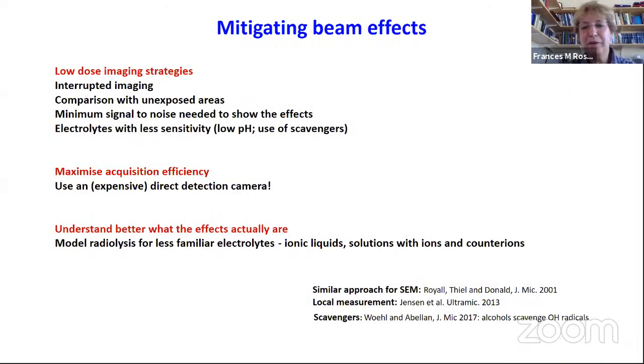So how can we mitigate beam effects? Well, there's no single solution, and so depending on your experiment, you should choose a good strategy. For example, you could use low dose imaging, which means don't keep the beam on, just take a quick picture and then move it away or turn it off. You have to compare with unexposed areas so that you know that what you see is real. You should always record the images with the minimum signal to noise that you need to show what you want to show. So beautiful images tend to require higher dose. And so when you see noisy images, you know the person is doing the job correctly.